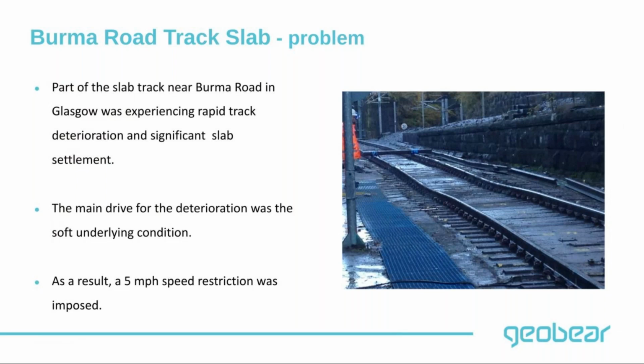Another case study, and that's the final case study in this presentation, is where we've done some work on Burma Road slab track. That particular location is somewhere in Glasgow, where there was about a 150 mm dip in the track. That's a massive dip, and you can see it's quite visible from the picture. The track was experiencing rapid deterioration, and as a result of this very poor track geometry, they had to introduce a 5 miles an hour speed restriction.